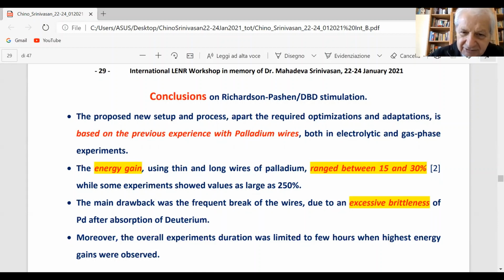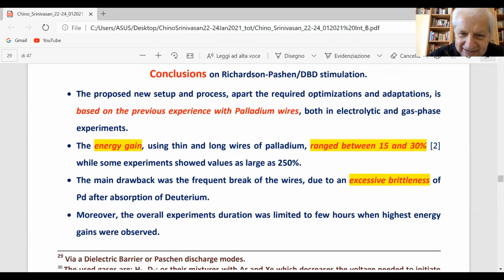Moreover, in pulsed condition, in a specific experiment, we increased the power and we got excess energy up to 250%, but for a short time because the palladium self-destroyed. But it means it will be possible. And it was at the temperature of electrolysis, so less than 100 degrees.